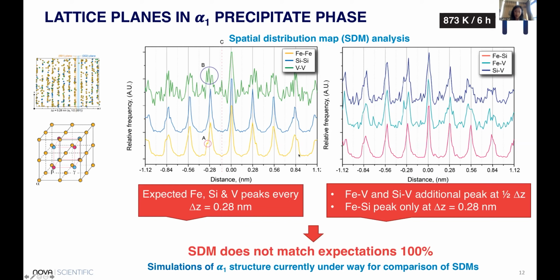Vanadium shows a variety of interatomic distances and seems to be offset ever so slightly from silicon. This could hint at vanadium occupying both corner and center positions. The spatial distribution map on the right side for an AB pair shows an additional peak at 0.14 nanometer steps for iron-vanadium and for silicon-vanadium, indicating again that vanadium may occupy corner and body center positions. In contrast to our expectations, however, iron-silicon does not clearly show a peak for 0.14 nanometer steps. This could be due to an evaporation artifact.